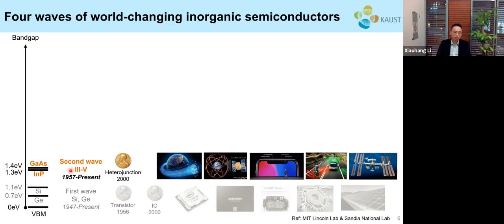Basically, it comprises elements from group 3 and group 5 from the periodic table. Those materials include gallium arsenide and indium phosphide with a larger band gap, about 1.3 electron volts. But in addition to having a larger band gap, those materials have a direct band gap as well. So this means that they can be made into LEDs and lasers with high efficiency, emitting at the wavelength corresponding to their band gap energy.